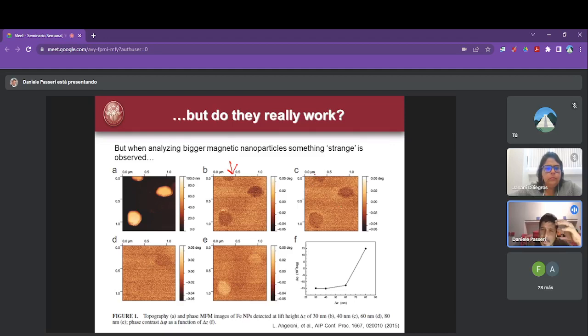When you increase the lift height, this contrast disappears, which somehow is reasonable, because if you go too far, you cannot feel the magnetic field anymore. But if you increase it again, those particles start to be bright, which is completely nonsense. It seems that at a certain point nanoparticles reverse their magnetization, so they are repulsive. I don't know.